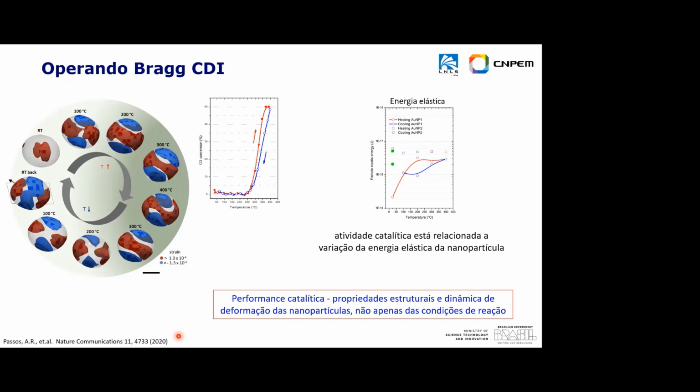how the nanoparticle is reorganizing and how it's related to this hysteresis behavior, which before was thought to be related only to external conditions like temperature or the kind of reactor. In this study we showed that it is also observed in a single particle. It's related, and we see how these tensile strain regions are formed and how long they stay in the system.